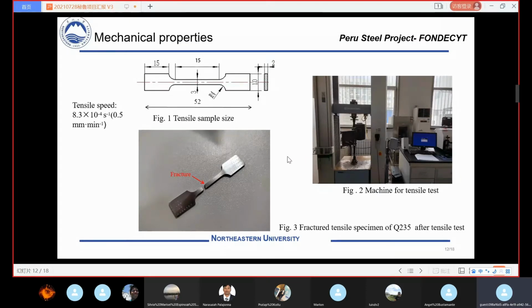The experiment is carried out at room temperature, and the tensile speed is 0.5 millimeter per minute. Before the tensile tests, we should polish our specimens with emery paper. After the tensile test, we can get such a sample, the fracture occurs in the sample. Actually, if we notice, this is in the middle of the sample.